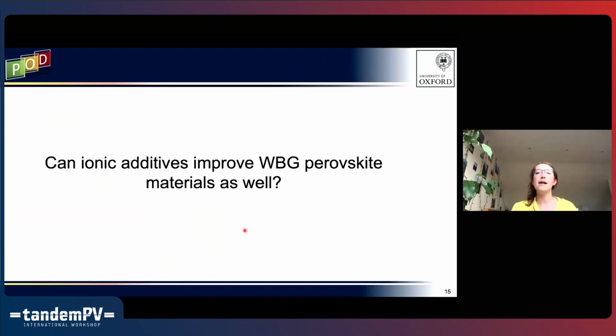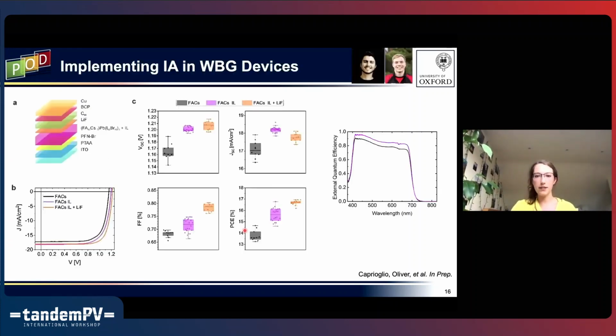So that's really neat. We've got really good stability from this ionic additive, which also increased our overall device performance. But then we had this question next of, can an ionic additive improve even wider band gap perovskite materials as well? This is some work from Pietro and Robbie, which is about to be submitted, so you get a sneak preview today. They're working on a FA83 cesium 17 lead iodide 60 bromide 40. Those numbers might be a little hard to see on your screen, depending on how small the video is. And using this ionic additive, they also saw really good device improvement overall.